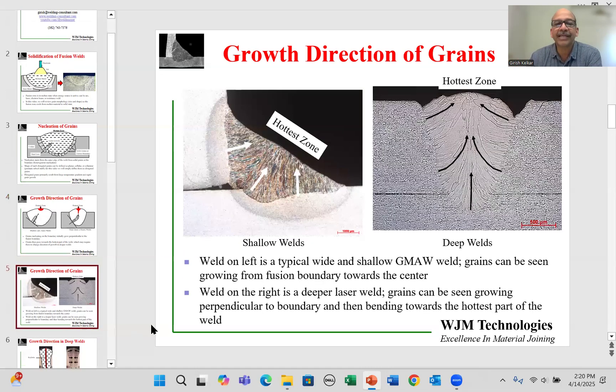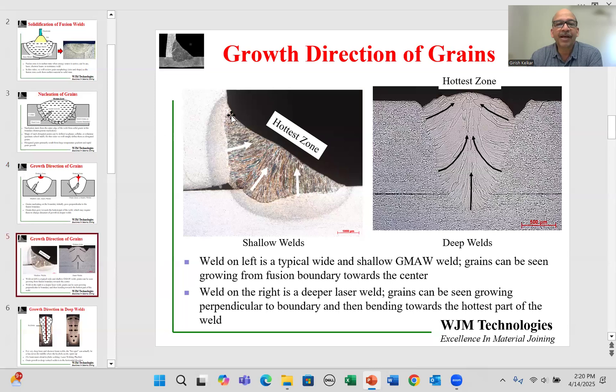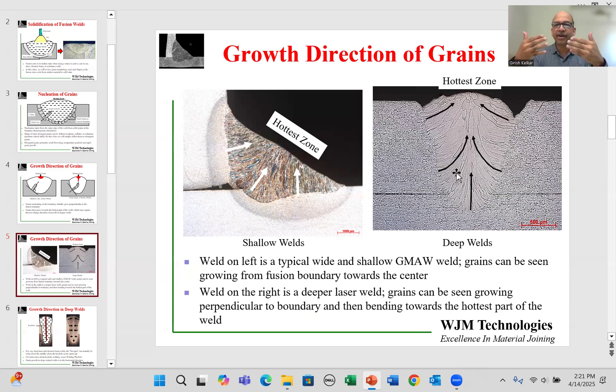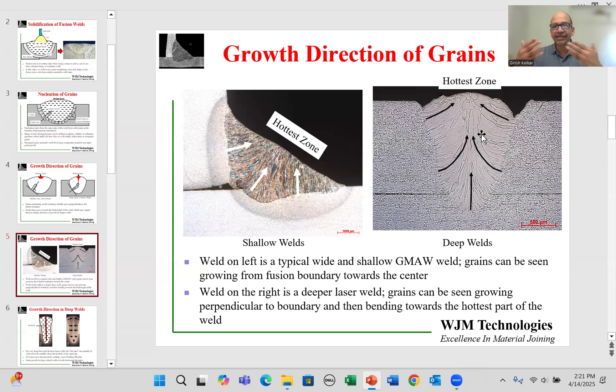This is a cross section of a gas metal arc weld, which is a shallow and wide weld. You can see that the grains growing from the outer edge start growing perpendicular to the fusion boundary and keep growing towards the hot zone, all going in the same direction. On the right hand side, I'm showing you a laser weld — a deeper, narrower weld. You will notice that at the deeper locations the grains do start growing perpendicular to the fusion boundary, but then actually turn and start growing towards the hot zone. Sometimes one grain starts growing and then it is taken over by another parallel grain that starts growing in a certain direction.